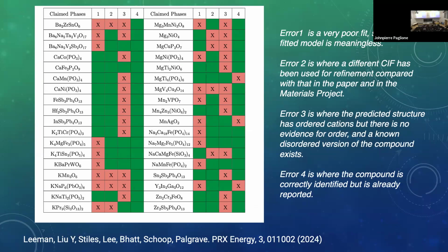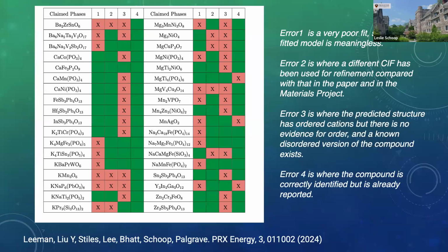Error 1 is a very poor fit to the data, so poor that you cannot say that this fit has any meaning. That's a pretty common error. Error 2 is that the CIF file that they use for the refinement is different from what they inputted. So I don't know how they did not catch this. They say this is this material based on Materials Project, and then you look into the refinement output file that was in the SI and it is a different structure. That's not that common, but it happened.